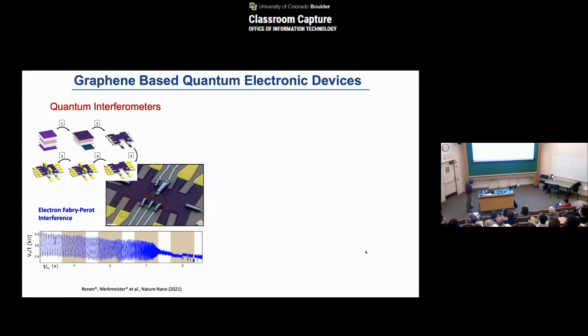This is about a micron or two. So this is a device oscillation. This is about kilo-ohms, and what we expect here is about 10% visibility of what we are seeing, compared with the zero that it is supposed to go to. So it's about 10% visibility. This one is tuned by the filling fractions, and the voltage is converted to filling fractions. The voltage applied on the top gate tunes the filling inside the top gate. So that's the way.